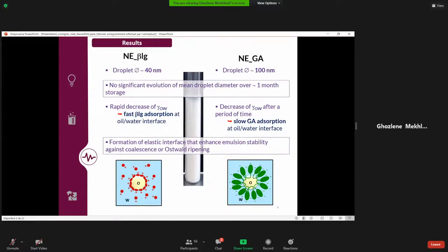And when we follow the time evolution of the interfacial tension, we see that there is a rapid decrease of the interfacial tension for the system with the protein. So the protein adsorbs very fast at the oil-water interface, while for the system with the polysaccharide, we note a decrease of the interfacial tension after a period of time. So the acacia gum adsorbs very slowly at the oil-water interface.